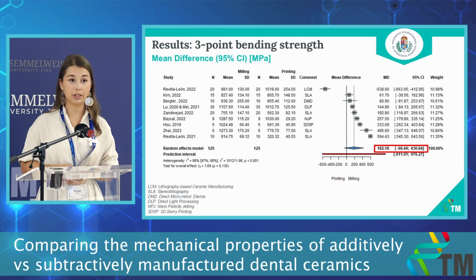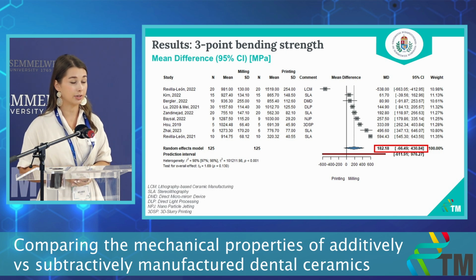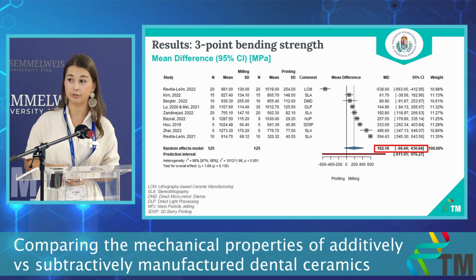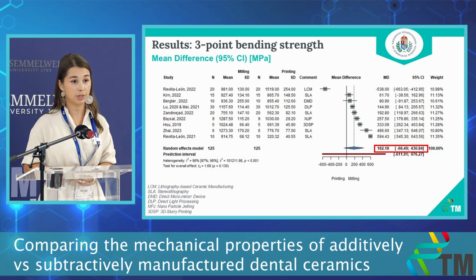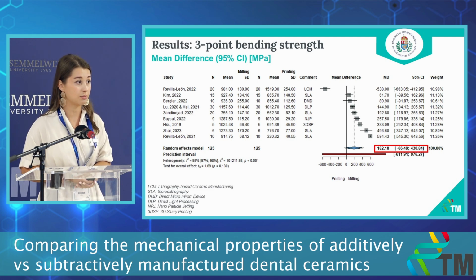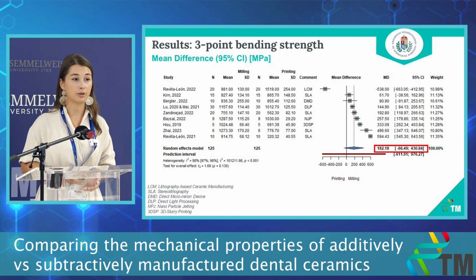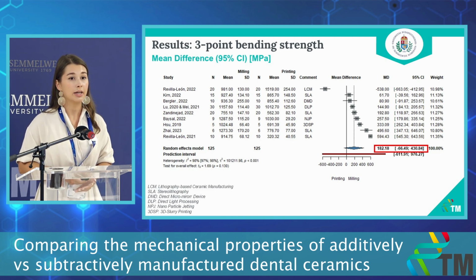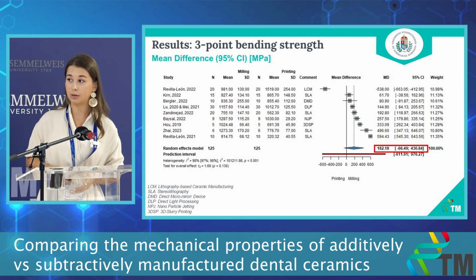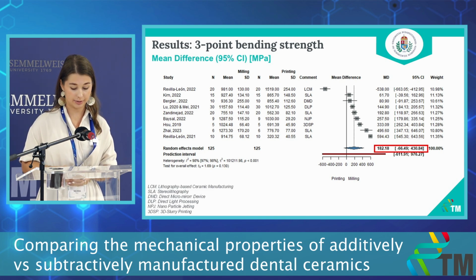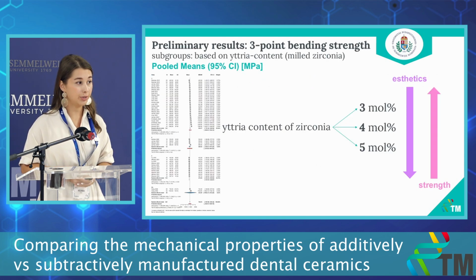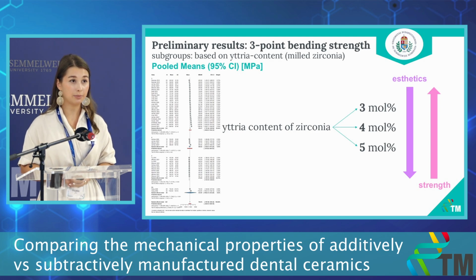We have an overall mean difference of 182 megapascals, and although this is clinically relevant, it hasn't reached statistical significance yet, meaning that printed zirconia is as good as milled zirconia. Although printed materials have come a long way and are really close to milled zirconia, there's still room for improvement, and they cannot be applied in the same indications yet. We included many 1-armed studies as well.